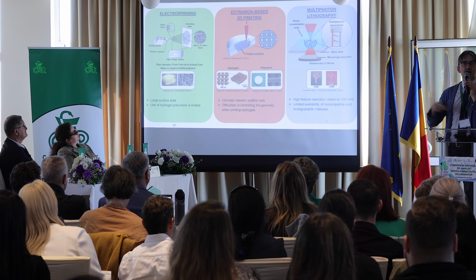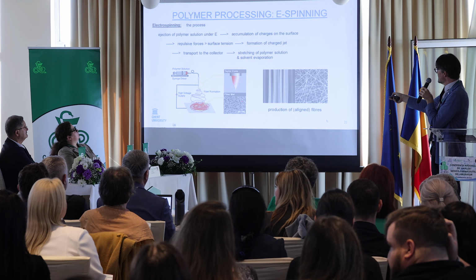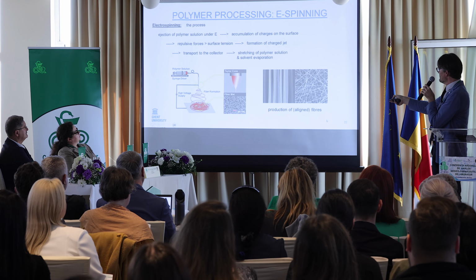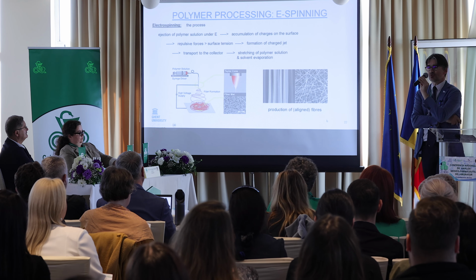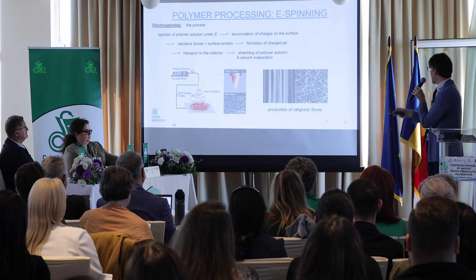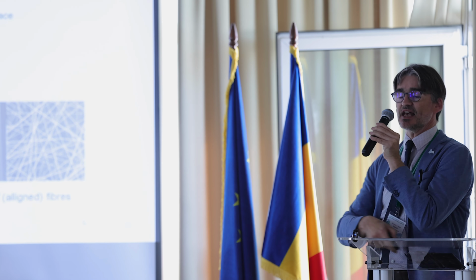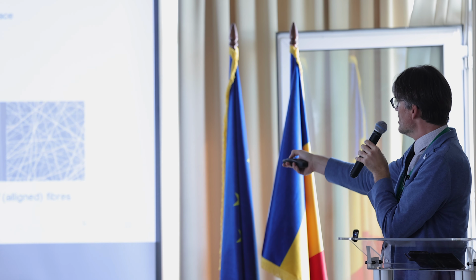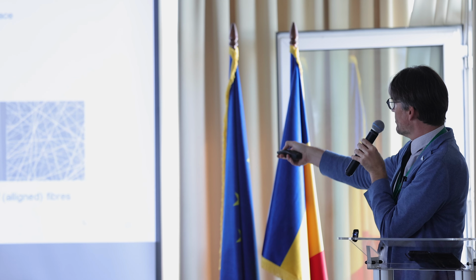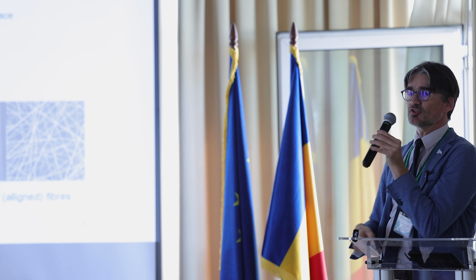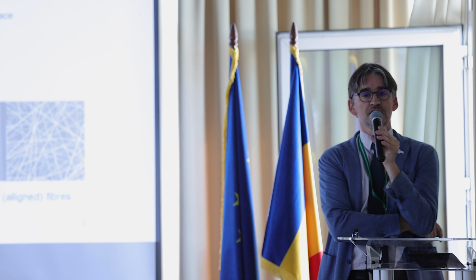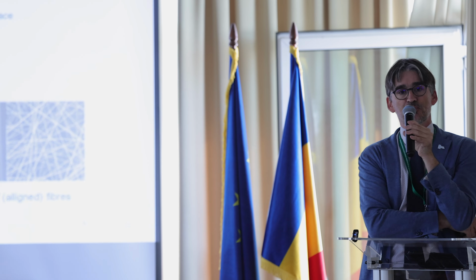So the first technique that we applied was electrospinning. In a nutshell, you start from a polymer solution, and after a complex process, you can obtain these type of fiber mats, which contain either randomly distributed or aligned fibers. And for certain medical applications, each of those architectures has their own benefits. Applications within the field of nerve engineering require aligned fibers. Many other biomedical applications require randomly distributed polymer fibers.